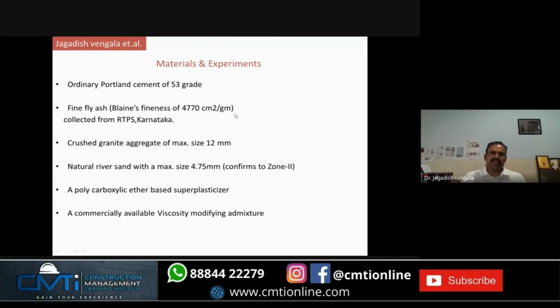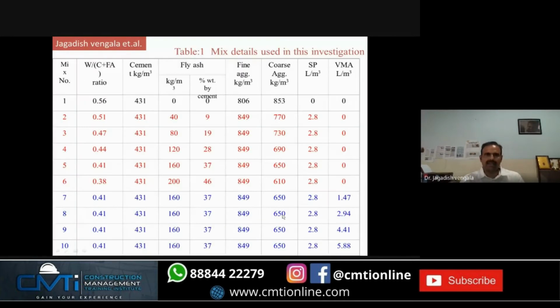So for our experiments in 2001, we took OPC, and Raichur thermal power station fly ash collected from Raichur, and 12 mm aggregates and natural river sand. At that time it was natural river sand; now all the sites are using crushed rock fines or other alternatives to natural river sand. We used a PCE based superplasticizer and a VMA. So these are the mixes you can see here.